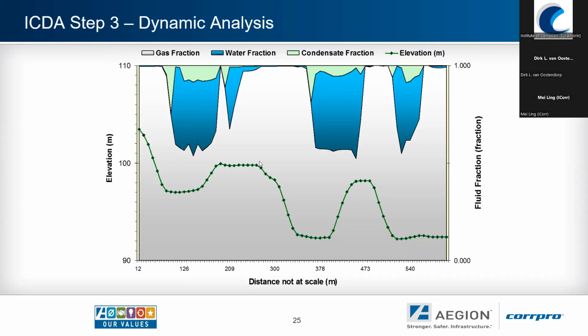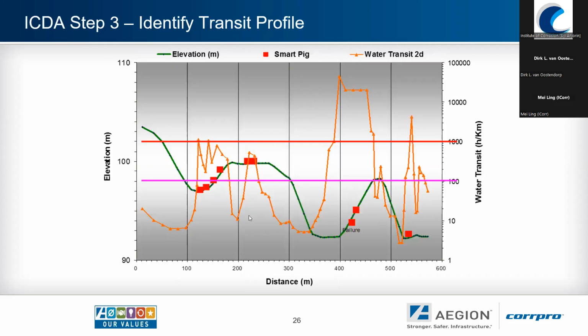So once we have the composition tracking, the next piece is to then project this out in a little bit more detail. And I mentioned the residence time of the water because that's a critical element to us. Even though I may have a high mole fraction of water, if that water is moving through the pipeline rapidly, it's not going to become a concern for us, or lesser of a concern than areas where I have trapped water. And so in this particular case, what we then did is use the transient simulated portion of the Olga model to take a look at the transit time of the water through there.